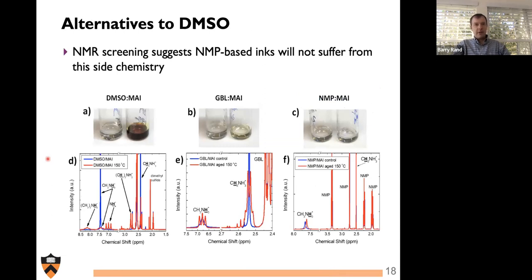In terms of screening alternatives to DMSO, while we don't have any clear-cut panacea for this, we can note definitely DMSO in presence of MAI is deleterious and leads to considerable reaction. GBL similarly will react with MAI, but NMP appears promising as not suffering from similar reactions compared to DMSO and GBL. And so we think that there is considerable promise to further develop NMP-based inks.